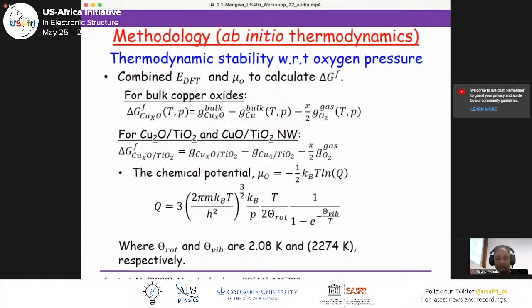Methodology. Now, the thermodynamic stability calculations are carried out with respect to oxygen pressure. This combines the DFT energy and the chemical potential to calculate the Gibbs free energy. The formulas for doing these calculations are indicated for bulk copper oxides and for the coupled nanostructures that are indicated there.